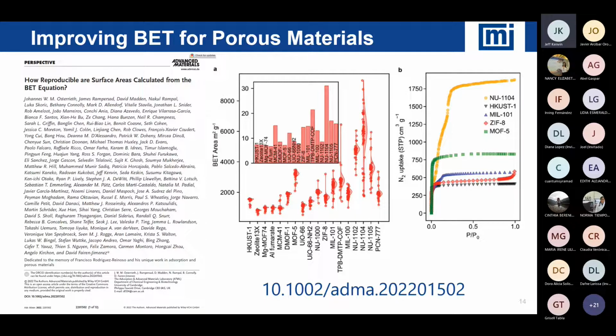So if you look at some common metal organic frameworks like HKUST-1, commercially, BASF sells that commercially as C300. We also commonly refer to it as copper BTC. You notice the reporting on that is quite good. The spread of surface areas is actually quite reasonable and small.